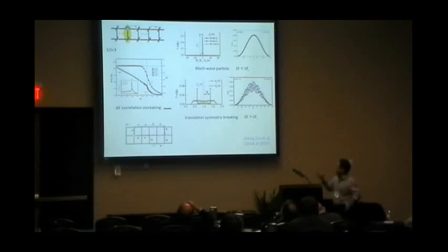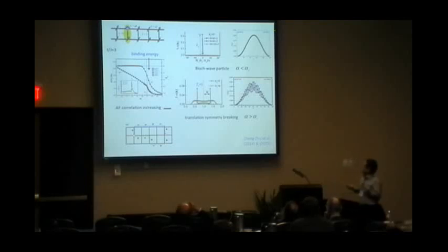This charge modulation can be easily understood by the phase interference of this loop. And this modulation is related to the spin background, but you see there's also a continuum background. It directly tells you this translation symmetry breaking. Because otherwise, if this is just a standing wave of two momenta, you wouldn't expect such a broad background. So you see that this is the case. If you put two holes in this system, you find that this modulation will be gone, but you get a strong binding on this side. But on the quasi-particle side, the binding energy is basically zero.